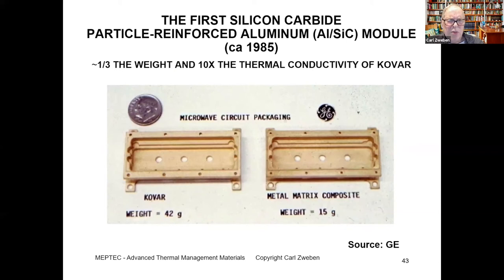What we had was a spacecraft which had many microwave modules. There was a big weight problem on the spacecraft. There were hundreds of modules, and they were all made of Kovar, which has a fairly high density and also a very low thermal conductivity. So again, we're trying to replace this traditional low expansion thermal management material with a metal matrix composite. In this case, we chose ALSIC, and we found weight savings of about 65%, 10 times the thermal conductivity of Kovar. It never went into production because the Kovar package was qualified and the money was not available to qualify the composite. But we published a paper on this in the 80s, and this stimulated a lot of interest in the industry.